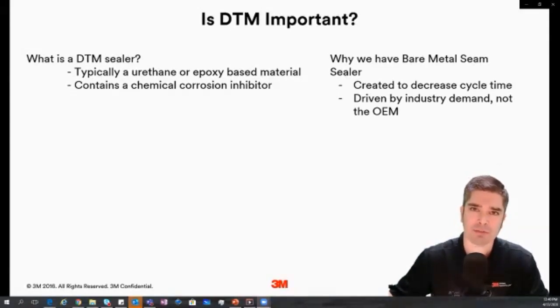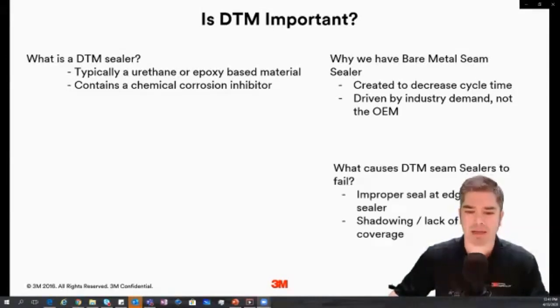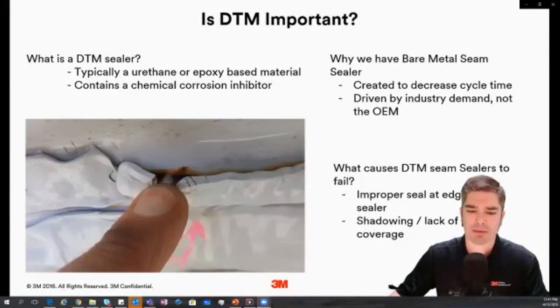They were driven by the industry, by the insurance companies' demand for faster repairs, for the customers' demand to get their cars back faster, for the shops wanting to improve their key-to-key cycle times. And really what we want to point out here is that they're not bad seam sealers, but we do see some misuse with them. One of the typical areas where we see misuse, or the reasons why a direct-to-metal seam sealer may potentially fail, is what we consider a lack of actual sealing at the edge of the seam sealer. So if you're trying to replicate any type of bead or appearance, and you don't get a good tight seal on that edge, you're allowing the potential for moisture to get in here.